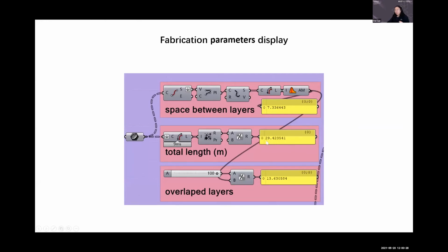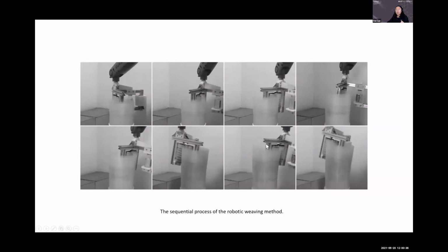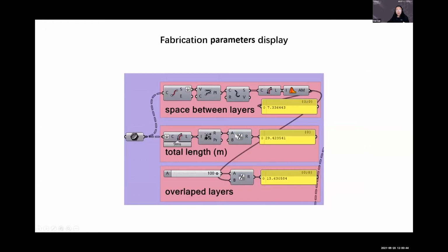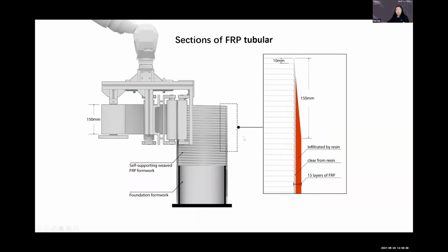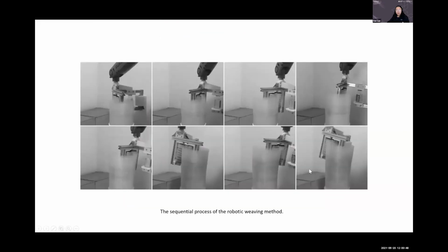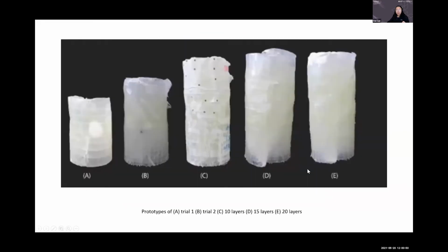Some of the main parameters that we calibrate, of course, are the total height and geometry, the space between the layers, and the distance of overlap between layers, in correlation with the different epoxies and different curing times during the fabrication speed. So this is the time lapse of the fabrication process.